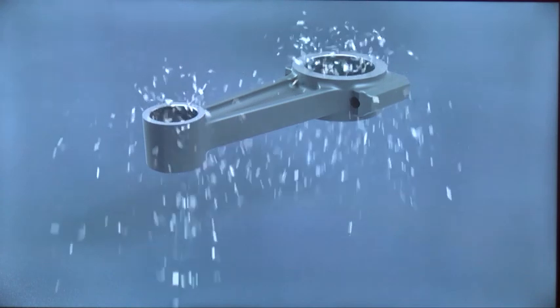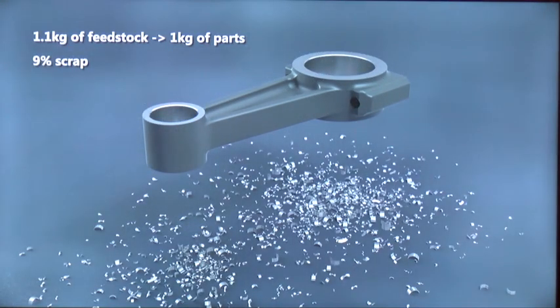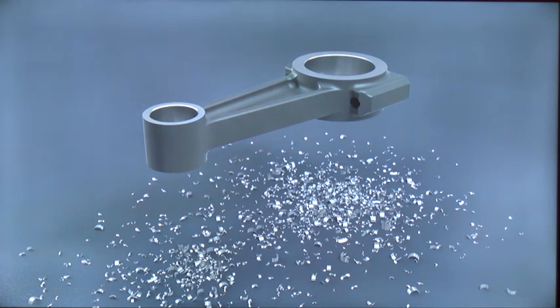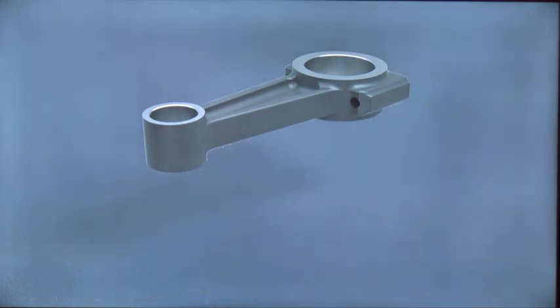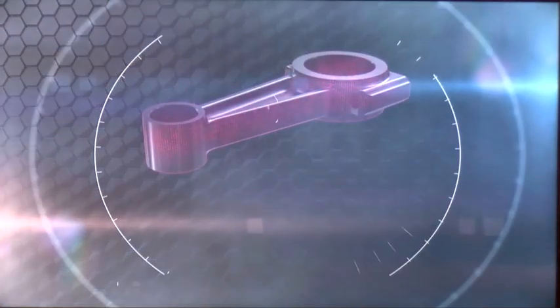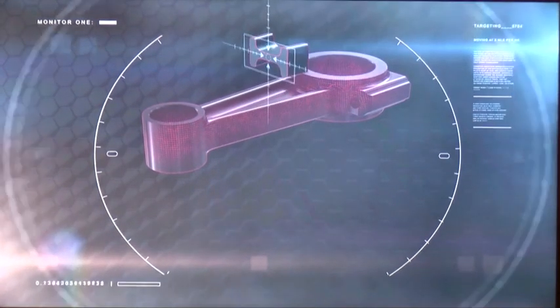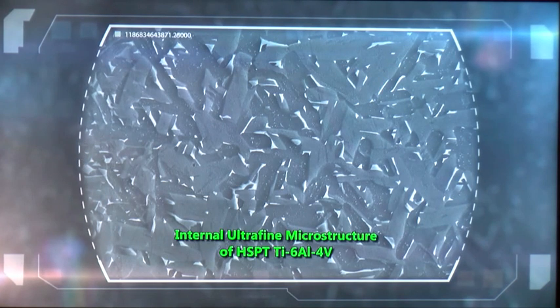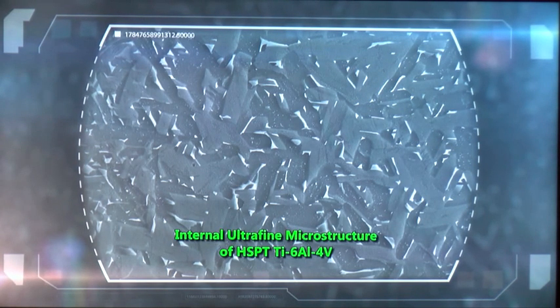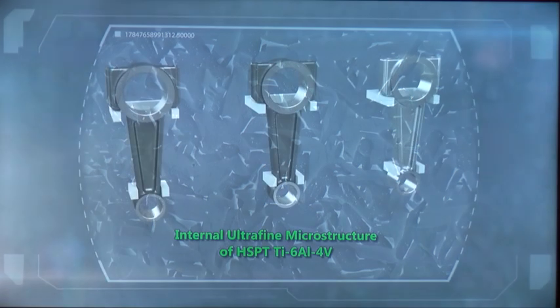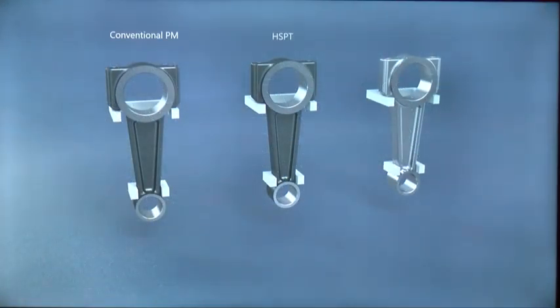So we get the advantage of having a near-net shaped part while also having the advantage of stronger materials due to the fine grains. And I'll explain all that in a minute also. So we still have the advantage of having machined parts, we have less scrap, and we have less machining steps. So here's our material where it's still that very fine material, and I'll have an image of that later that has all of them side by side. But you can see that ours is a lot smaller than vacuum sintering standard.